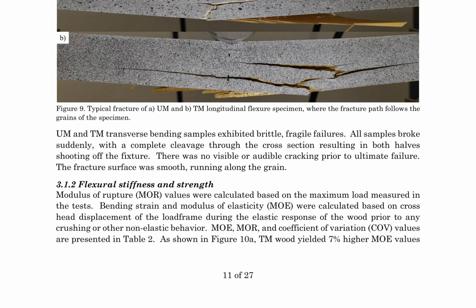The results suggest that thermal modification affects the mechanical properties of wood, particularly in terms of brittleness and deformation behavior. Thermally modified wood exhibits a more brittle behavior, with quicker failures and less deformation prior to ultimate failure, whereas unmodified wood withstood more deformation and cracking prior to failure.